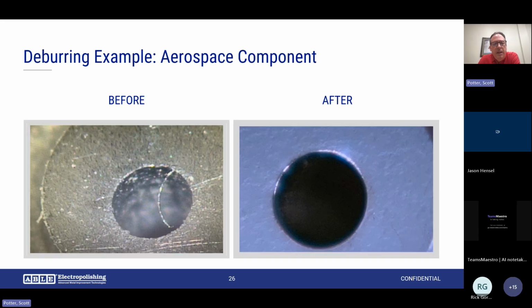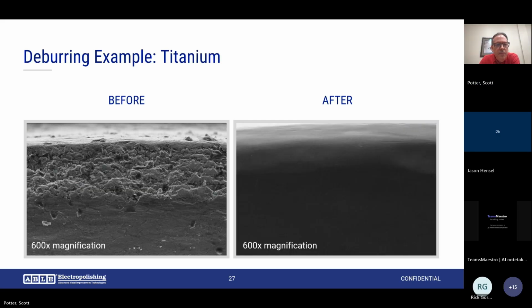With deburring, the big thing is it's not necessarily the height of the burr that's critical. It's the base of the burr. How substantially is it attached? It's kind of like a little whisker. We're able to clean up not only the burrs but also improve the micro-inch finish on this aerospace component. Here's a before and after deburring example on titanium under high magnification. It's pretty astounding when you go into the SEM and see what's going on microscopically.